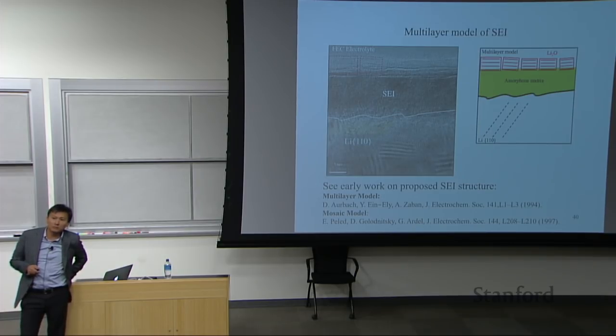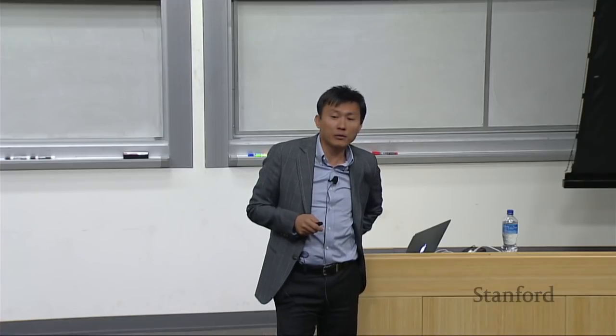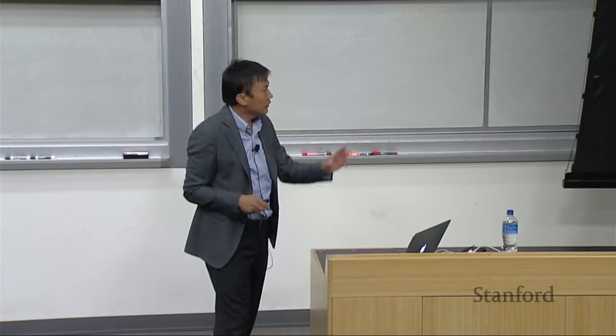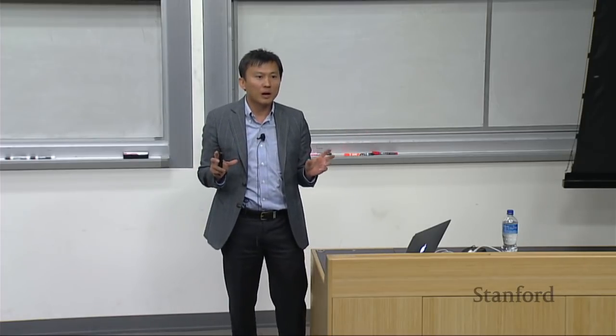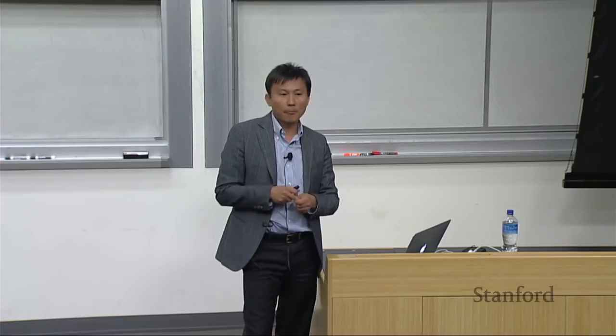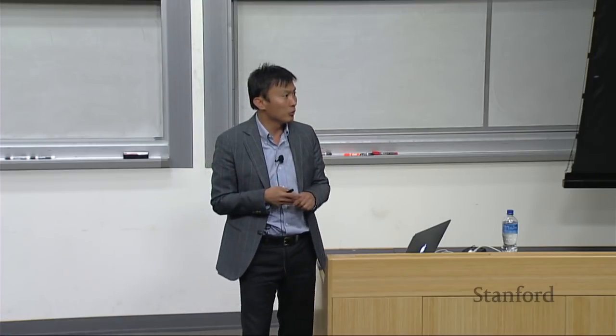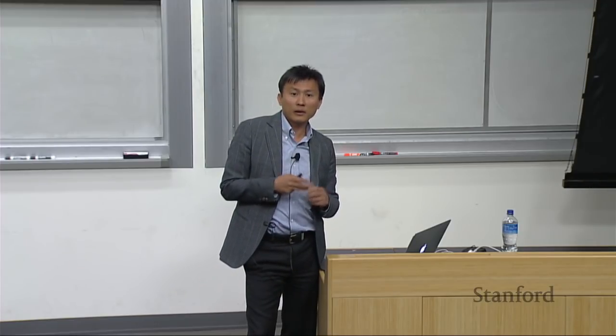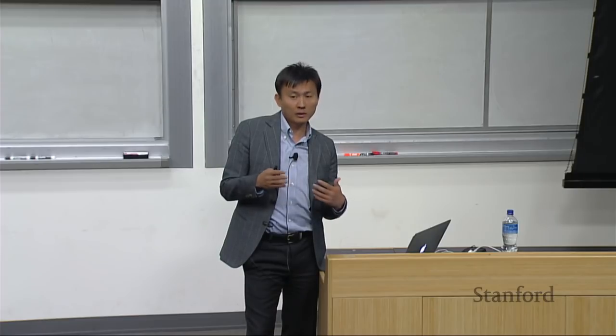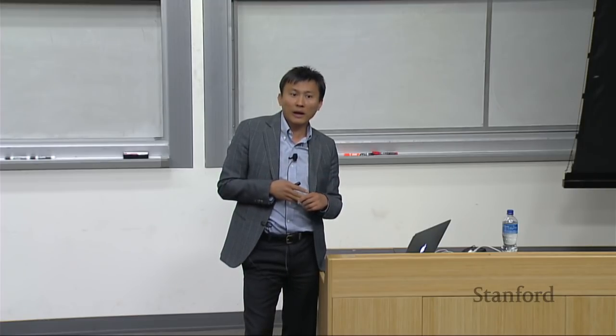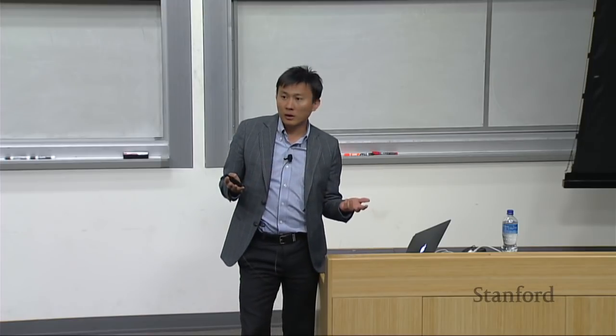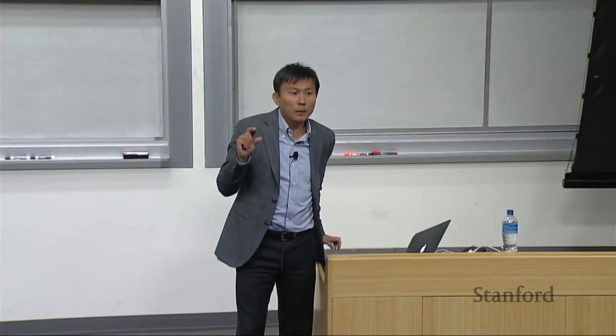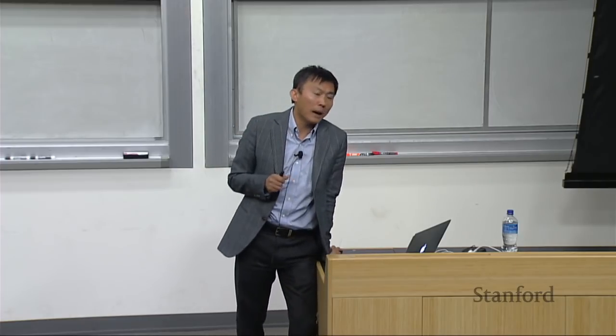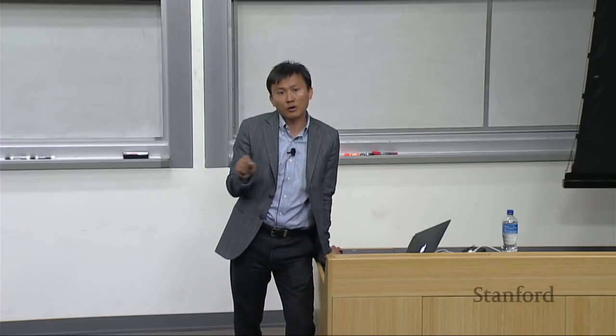Why is this important? Recent data, unpublished yet, from my talented graduate students, they're sitting right there. They see these two different morphologies, and they give you different interfacial impedance, resistance to the ion movement. That will change how the battery material, such as lithium metal, plates, what its morphology is. And that can change the efficiency of the plating and stripping, so-called Coulombic efficiency. That can determine your battery cycling life, whether long or short.